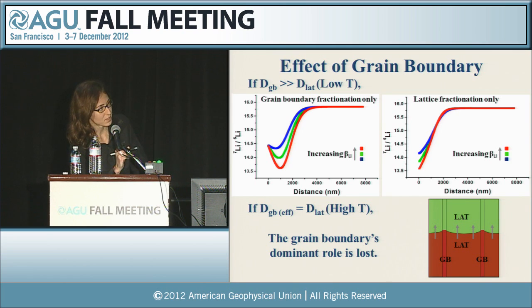So what's not shown in these images is the fact that when the grain boundary diffusivity is so much higher than the diffusivity in the lattice, the grain boundary really holds the dominant role in determining what the isotopic composition of the lattice is at the end of the model. So that's when the grain boundary diffusivity is much higher than the lattice diffusivity.